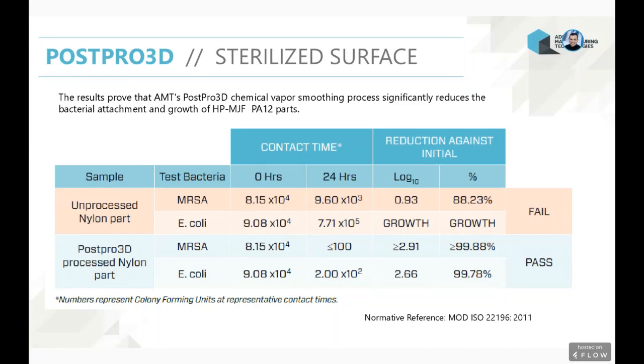If a part was fully saturated with Blast-X, which is the chemistry we're using, the consumable that we use for PostPro3D, what would happen? And even under that scenario, with a part that has been fully saturated with Blast-X, we still are able to pass the cytotoxic testing. And we can share all these results if you are interested in them.